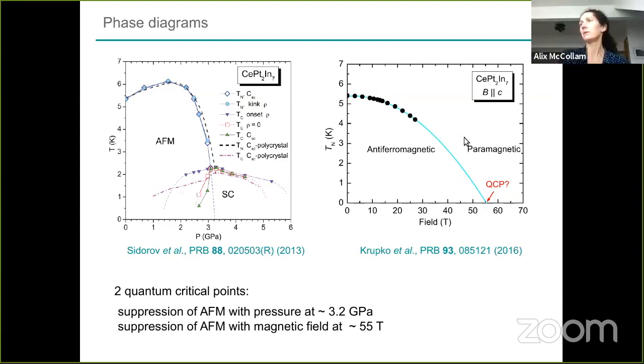The superconductivity, Piers had a question about the superconductivity in cerium platinum-2 indium-7. It looks like it's d-wave. It seems to be quite similar to cerium rhodium indium-5 in most respects. The TC is about the same. The critical field is about the same.